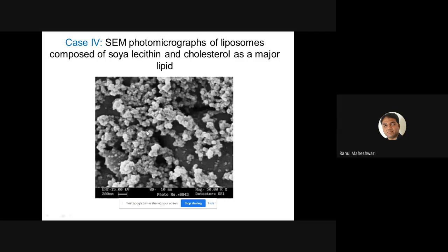And after looking at the image, we may think that this is not a good formulation. There is a degree of agglomeration over the particles. I mean, the distribution is not clearly seen. But this is not the case. Why? Because particle size is very small in this case, right? So we can interpret that this is a good image, giving the uniformity, and it is showing the importance of the method as well.